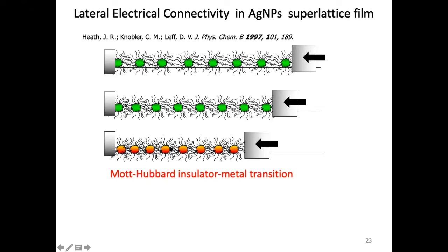Well, this is basically a hypothesis, but how am I going to measure it? The Heath group is very famous for that. What they did was use reflection of a laser on the film. They took this film on a Langmuir-Blodgett trough and reflected the laser. You know that metallic character means very high refractive index, so a metal reflects light. So they just shined the laser on the film when it was insulating, when there is not much contact between the particles. You don't see any reflection of the laser on the surface. But when you compress the film and it is close enough, you start getting reflection of the laser beam on the film.